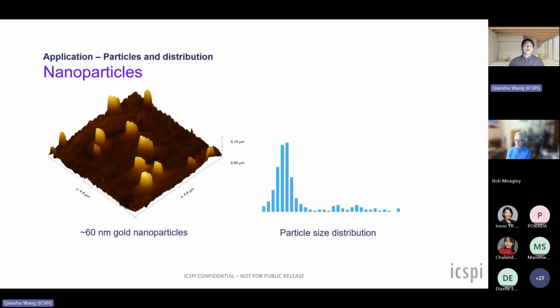The other aspect that AFM is really good for is looking at particles. I'm sure many people here are familiar with various particle size analysis techniques like DLS. These are very good for giving you an idea of the effective size of particles. AFM can also give this information, but besides that, it can give you a sense of the particle size, the particle size distribution, how these particles are distributed, as well as the specifics of their particle shape. You can see here on the left side, the 60 nanometer gold nanoparticles. This can be compared to other techniques like transmission electron microscopy, which is commonly used for particle analysis, but can often be very expensive and involve a much higher investment.